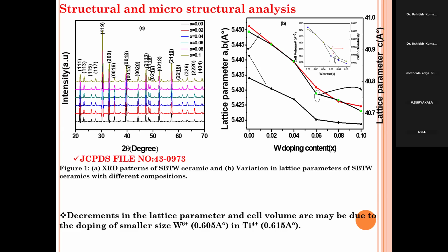Then this is the XRD. When we place the tungsten on the titanium side, from the XRD analysis we found that the pure SBT and the tungsten-doped SBT XRD peaks are the same. That means no structural deformation happens in that material. So the pure structure is formed when we place the tungsten on the titanium side.